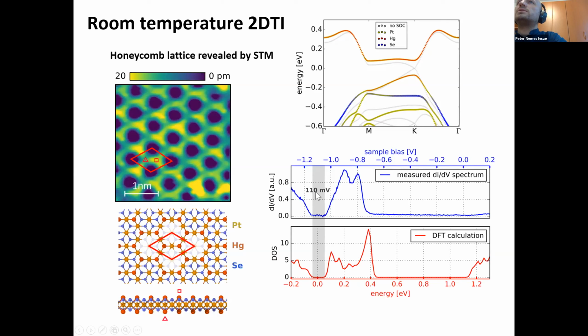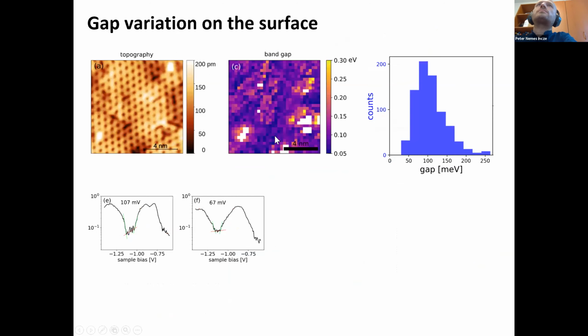So at the moment, the gap is not at the Fermi level, but well below it. But this gap is quite large. It's of course much larger than room temperature, and due to the disordered nature of the crystals, meaning it has quite a few lattice defects, as you can see here in this scanning tunneling microscopy topography image, the band gap tends to vary from site to site.